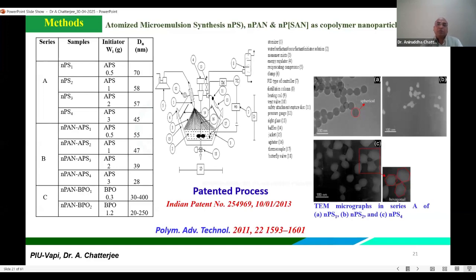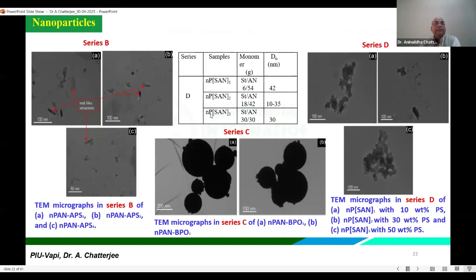with the help of atomized microemulsion process, where this is the polyacrylonitrile nanoparticles with the help of APS, meaning ammonium persulfate, as an initiator, and this one is with the help of benzoyl peroxide as initiator. So as we change the initiator from APS to BPO, you can see the morphology changes from crystalline to amorphous, meaning from crumb-like structure to spherical-like structure. And here a mixing of crumb-like and spherical structure is present when we are synthesizing the copolymer of styrene and polyacrylonitrile as copolymer nanoparticles.